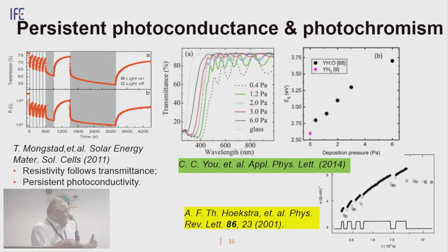And since we were interested in solar cell applications of this material, we studied electrical properties as well. We studied electrical resistance. What we found is that electrical resistivity is changing synchronously with the transmittance. When the light is on, conductivity is increased. When the light is off, it was decreasing to the initial value.